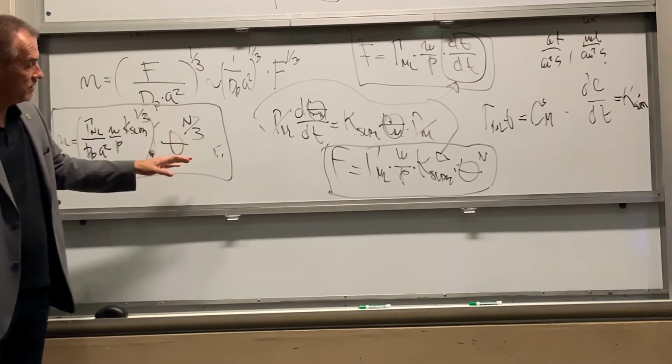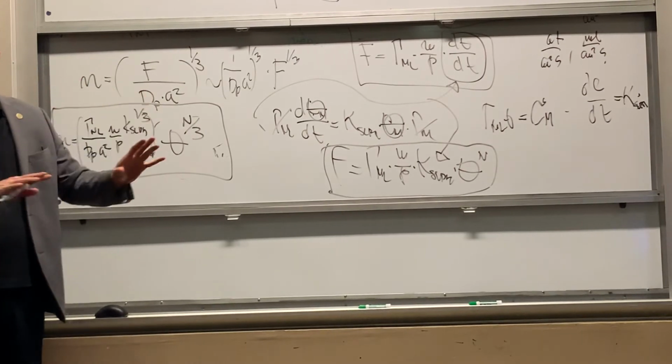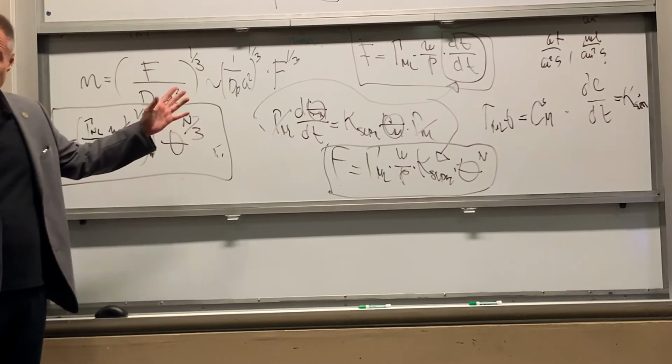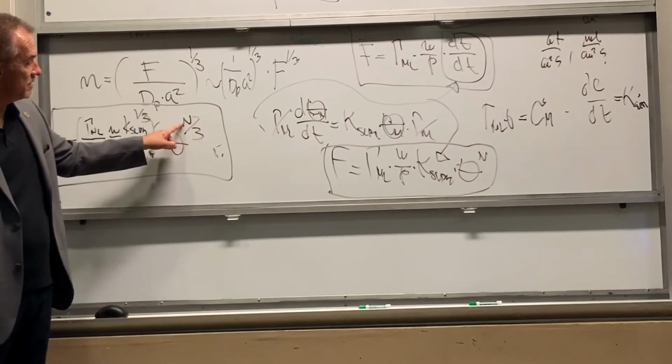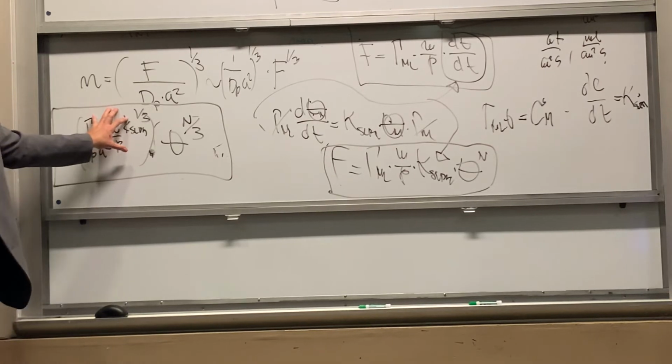And I could fit my number of clusters, so nucleation density, as a function of theta, and I should be able from this relation to come up with the exponent and extract the order of the reaction, right? And I would be able also to get this constant too, right?